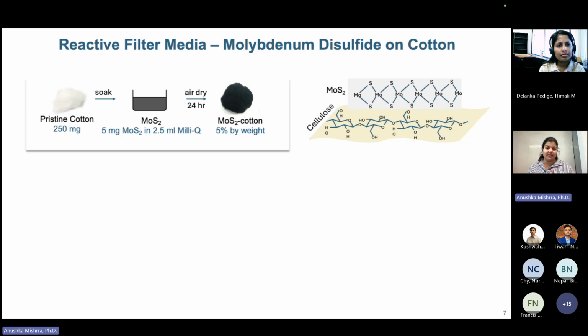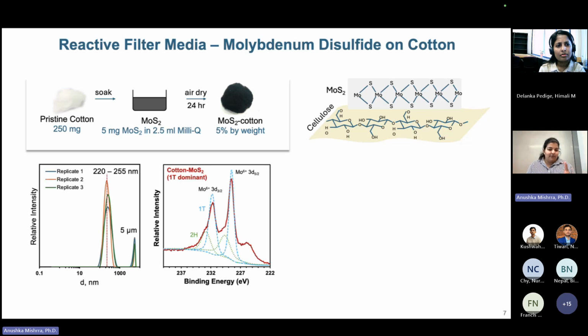But during the synthesis process, we were able to coat a good amount of MOS2 onto the cotton, which we think would be able to react with chromium-6 during the treatment. So part of this work involved characterizing this material.